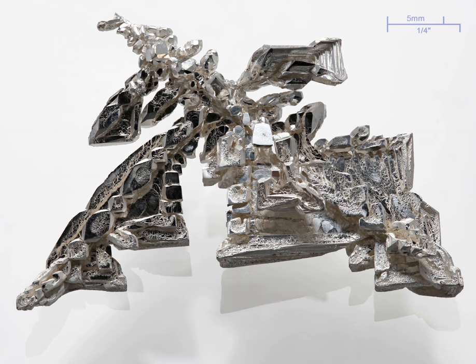For example, in copper production, purified copper is electrolytically deposited on the cathode, while the less reactive precious metals such as silver and gold collect under the anode as the so-called anode slime. This is then separated and purified of base metals by treatment with hot aerated dilute sulfuric acid and heating with lime or silica flux, before the silver is purified to over 99.9% purity via electrolysis in nitrate solution.